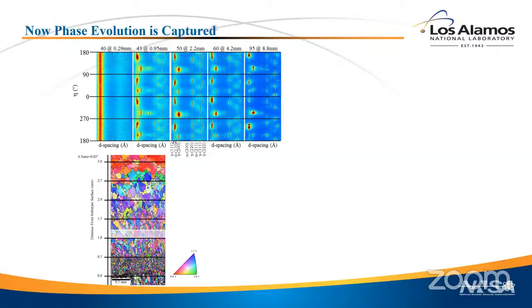Stainless steel, or I should be careful, 304L stainless steel is a ferrite former. It solidifies as ferrite and then transforms to austenite. If you talk to welders, that's really important. That's everything in welding steel. If it forms as austenite and then turns to ferrite, then it'll fracture. So that's why you actually control the temperature in this steel, to make sure it forms as ferrite first and then transforms to austenite.